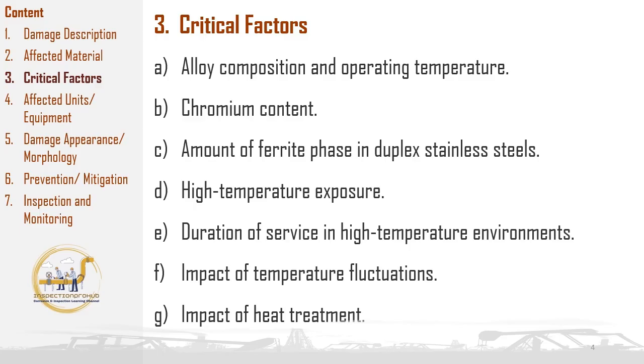The presence of a ferrite phase, especially in ferritic and duplex stainless steels, also increases susceptibility to embrittlement at these temperatures, as ferrite can transform into brittle phases that weaken the material. The operating temperature is equally critical. Prolonged exposure to temperatures in the embrittlement range allows for phase transformations that reduce the steel's ability to absorb stress, increasing the risk of cracking and failure. Hence, proper control of both alloy composition and temperature is essential to mitigate embrittlement and maintain material integrity in high-temperature environments.